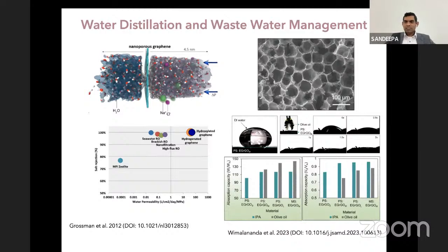Once the water is contaminated with oil, still the graphene material is quite an interesting material for this one because we can see we have a synthesized graphene form and this performance is quite high, and the absorption capacity is almost more than 100 times compared to the oil absorption capacity in graphene.